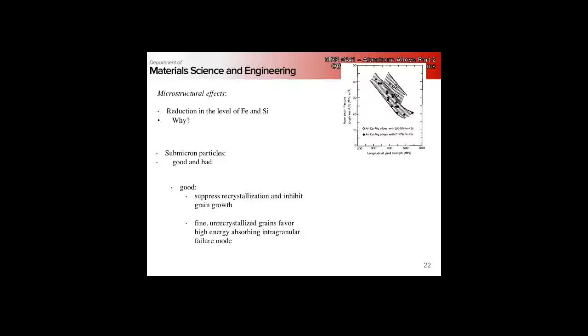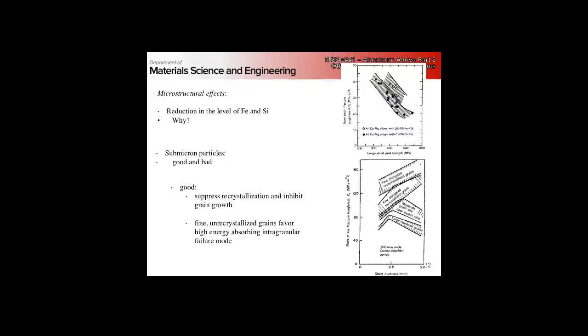Okay. The good about this is, again, we suppress recrystallization, and then these fine unrecrystallized grains, when they do fail, will favor this intragranular as opposed to intergranular failure mode. So the cracks will cut across grains rather than going along the grain boundary. And so we can see here again, this is fracture toughness, and we can see here the fine elongated unrecrystallized grain.